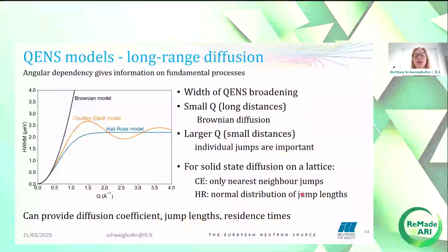For long-range diffusion, the angular dependence of the half-width at half maximum can give us information about the details of the diffusive process. At small q, so long distances in real space, Brownian diffusion is dominant. But as you move to larger Qs, so smaller distances in real space, individual jumps become more important. This means that at large Qs, we can differentiate different types of diffusion.